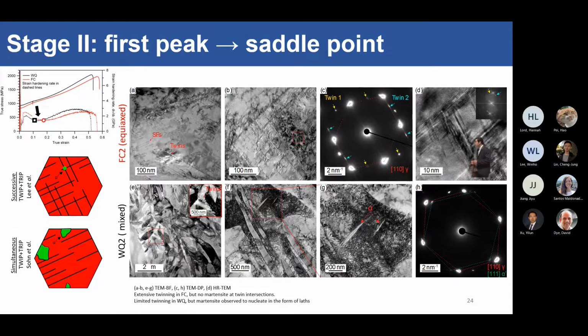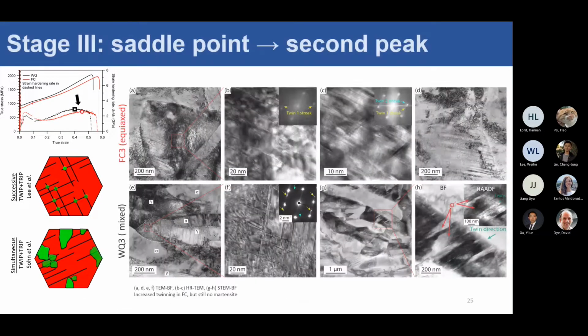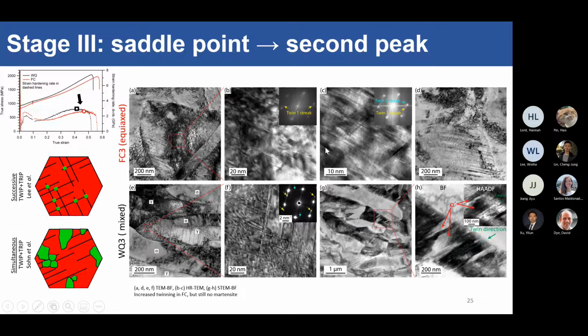Right, in the water quench sample, there are very few twins. There's hardly any twinning in the lamellar austenite grains. You only see maybe just a little bit of martensite forming in there, but nothing really much going on in there other than forming dislocations. So now we go to the second peak here. So in the second peak, we look at the austenite grains again. You can see there's some twins in there, just maybe a trace of the second twins going across, but again, no martensite in these grains.